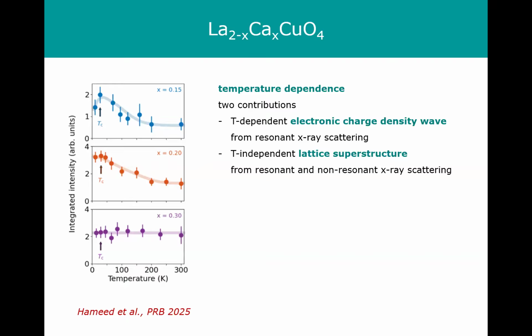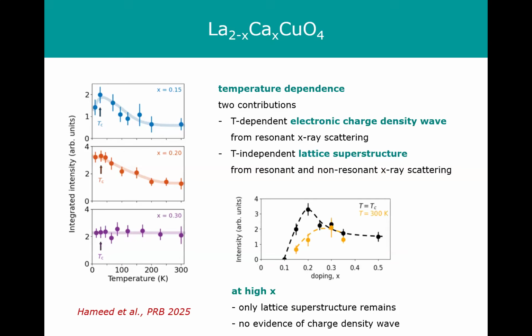Okay, and to confirm the origin of this superstructure at high doping levels, we also performed non-resonant X-ray scattering experiments that are sensitive to all electrons, core electrons, valence electrons, etc. And they also saw clear evidence of this superstructure. So that confirms that it's really a lattice superstructure, not charge order.